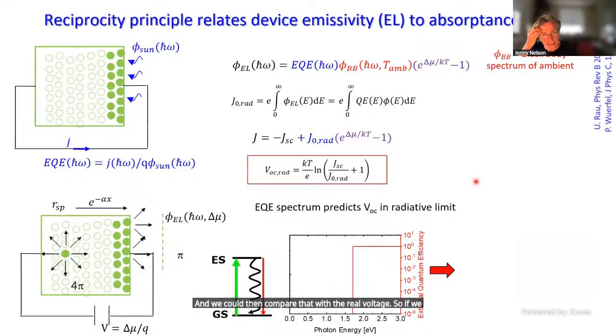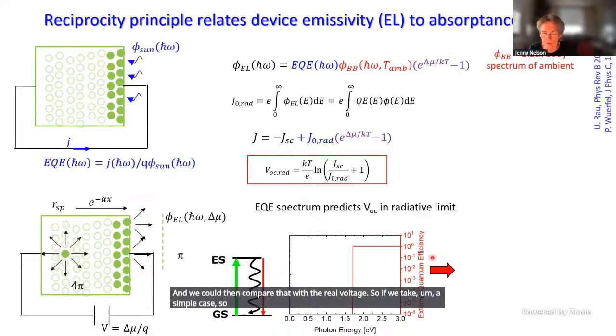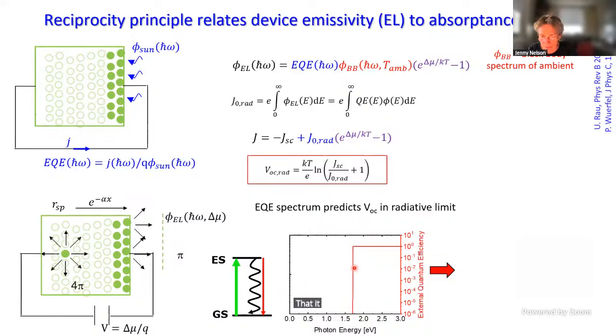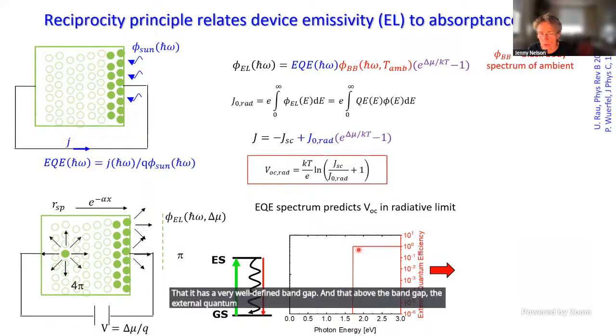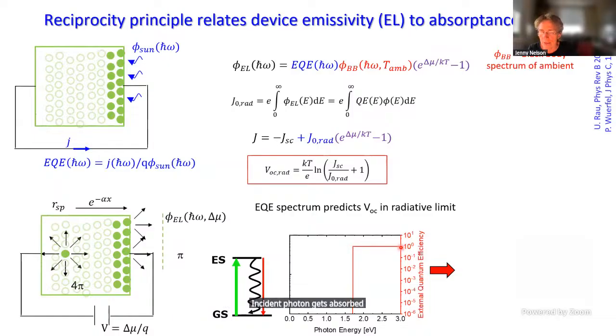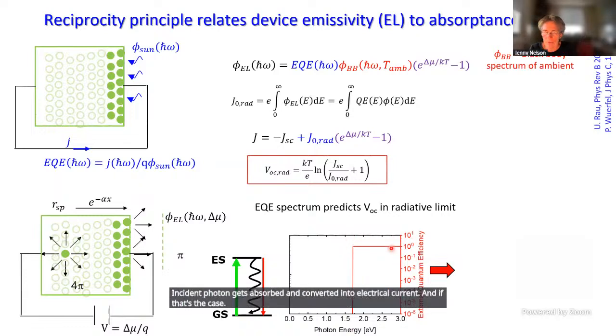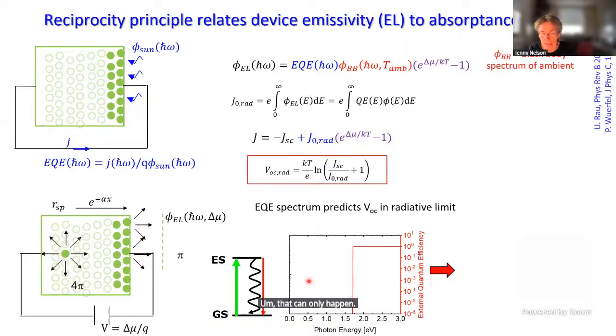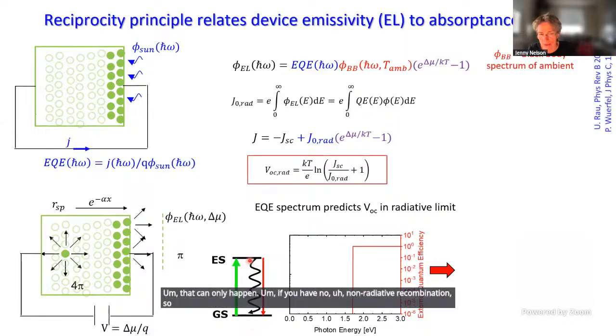So if we take a simple case, in the case of Shockley and Queisser, when they considered an ideal solar cell, they make the following assumption. They assume that it has a very well-defined band gap, and that above the band gap, the external quantum efficiency is 1. That means every incident photon gets absorbed and converted into electrical current. And that can only happen if you have no non-radiative recombination. So my squiggly line here, that should not happen.